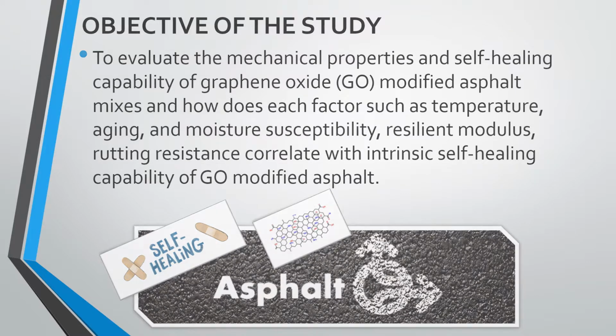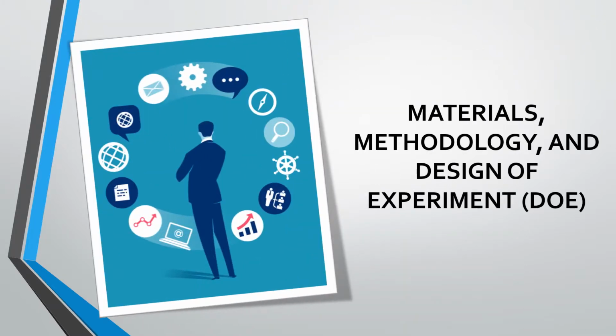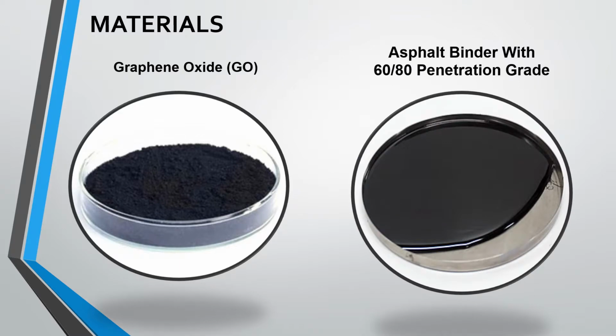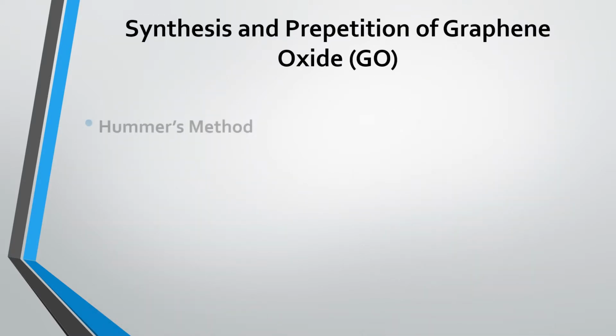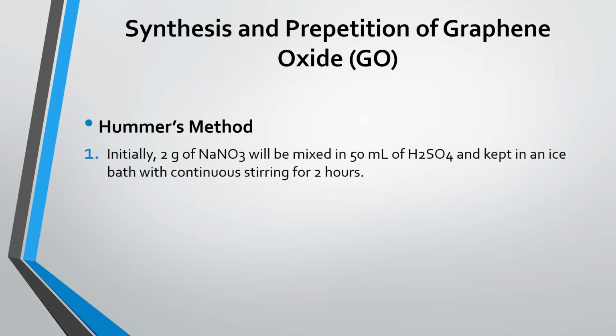To carry out the objective of the study, here are the materials, methodology, and the design of experiments that will be used in the study. The study will synthesize graphene oxide using Hummers' method. Initially, 2 grams of sodium nitrate will be mixed into 50 ml of sulfuric acid and kept in an ice bath with continuous stirring for 2 hours.